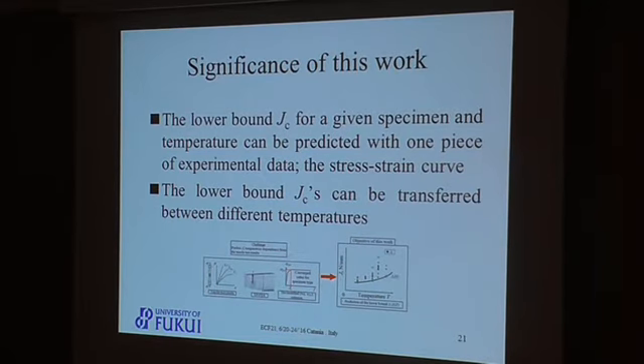In the former presentation, I said only one experimental data, but it's my poor English. If we use different temperatures, we need different tensile test properties for different temperatures. But the kind of experimental data we need is the stress strain curve. And second, the lower bound JCs can be transferred between different temperatures. And this was presented in another work at this conference.